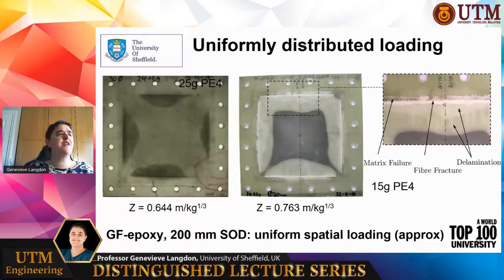Just to illustrate that a little bit further, we just saw some images of panels where the explosive was very close to the target. In these tests, the explosive has been put further away, at 200 millimeters away instead of 50 millimeters away. And in these tests, we can see that you don't get any localized damage in the center of the panel anymore because the panel has been subjected to a more uniform load across its front. Here on the left-hand side, we've got a panel subjected to 25 grams of PE4. On the right-hand side, a panel subjected to 15 grams of PE4. And you see the front face on one and the back face on the other.